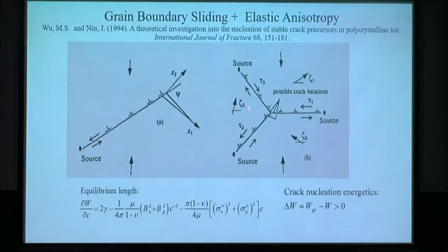In analogy to the classical work, we have dislocations piling up against perhaps an obstacle, such as an inclusion. Here we are piling up against a triple point. Now we can analyze each dislocation, or we can use a continuum approach, in terms of dislocation densities. Based on this model, there are some details. We can calculate the equilibrium length, and we can calculate whether the length so predicted could actually arise.